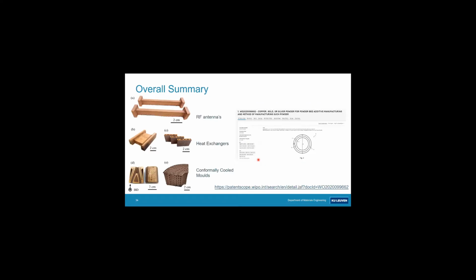These are a few parts which Suraj also made. So radio frequency antennas, and what is very important there is that they are very straight. And surprisingly, in copper, actually, in general, in the highly conductive copper, the residual stresses in your parts are surprisingly low, despite the fact that it's a very high conductor and the large heat dissipation. We also patented part of the procedures here, so you know, that is nice as an output.